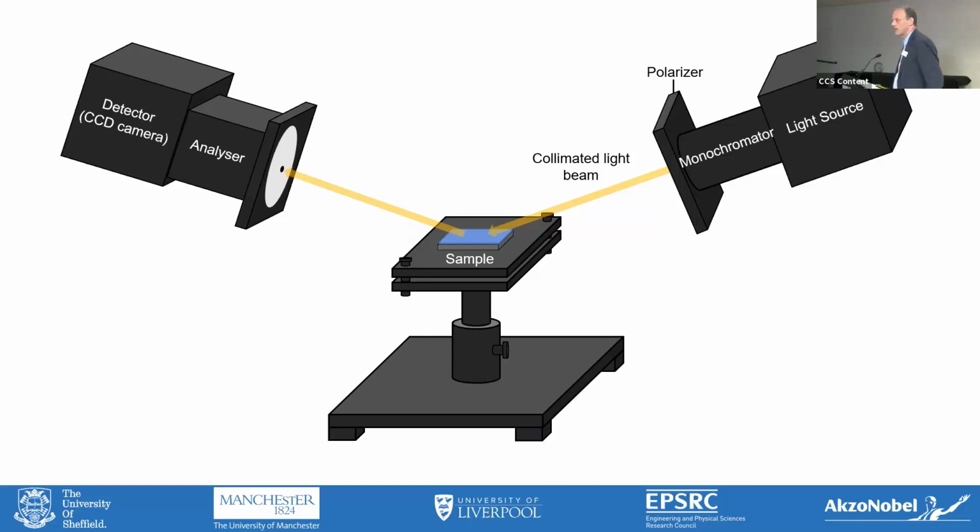So you're depending on being able to use an optical technique with a wavelength of 500 nanometers or whatever, and you're expecting it to tell you about a length scale of order a tenth of an angstrom is probably about right. So it's astonishing it works at all.